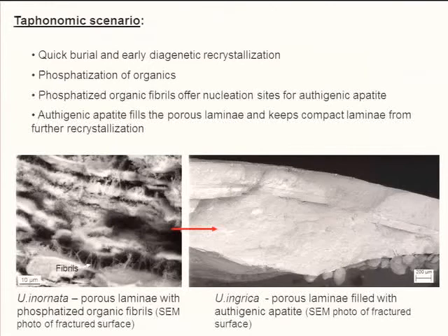The apatite in compact lamina is represented by original skeletal apatite, which has been recrystallized but may still have preserved some of its original characteristics. The apatite in porous lamina is mostly represented by authigenic apatite, or a mixture of skeletal and authigenic apatite, which may have been further altered by diagenetic fluids because of the porous nature of these lamina.